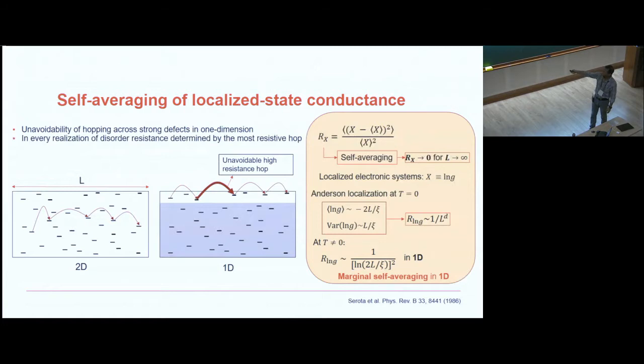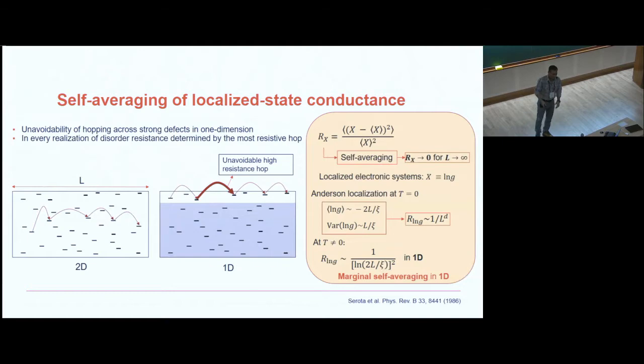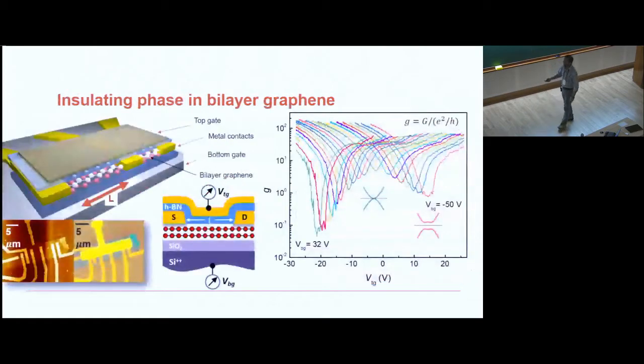So in the case of a localized electron system, it is the log of G, where G is the conductance in units of e squared by h. If I have a localized system, then in higher dimensions it goes as 1 over L to the power of D, whereas in 1 dimension, simply because you cannot avoid these large resistance hops, this number decreases very, very slowly, as a logarithm. So this is a beautiful way of seeing the dimensional effect. Okay. So this is what we looked at very quickly.